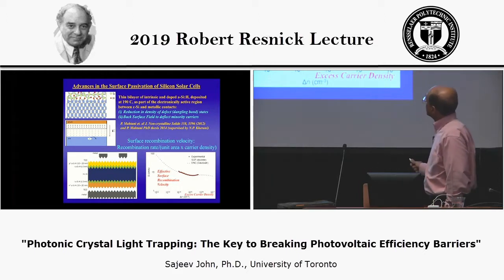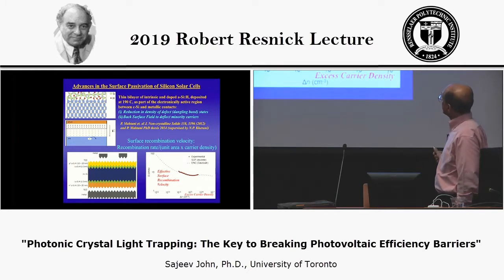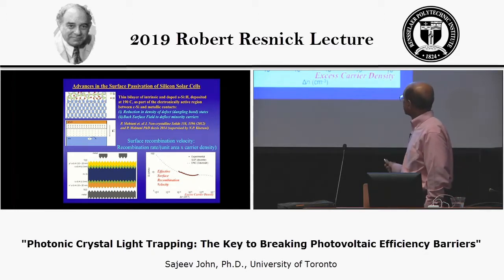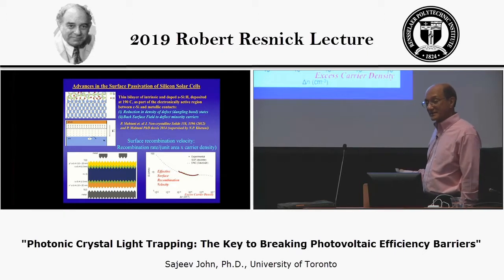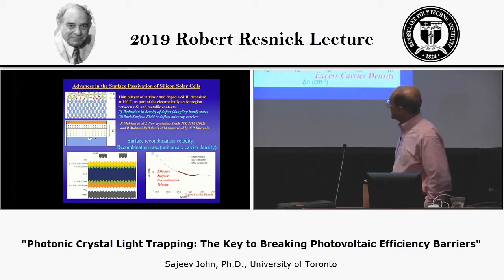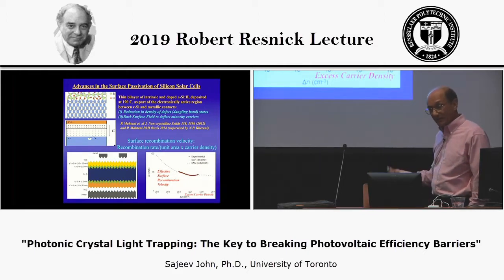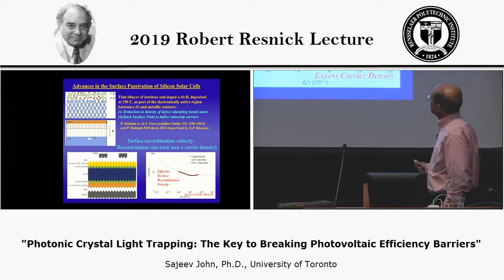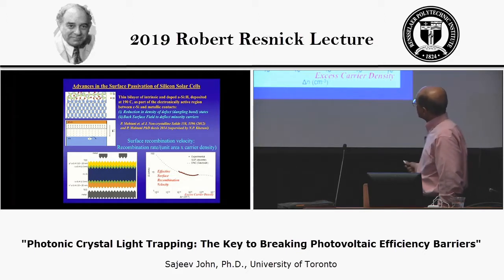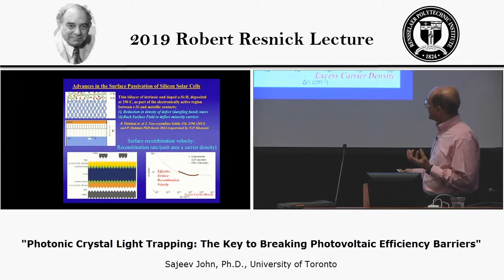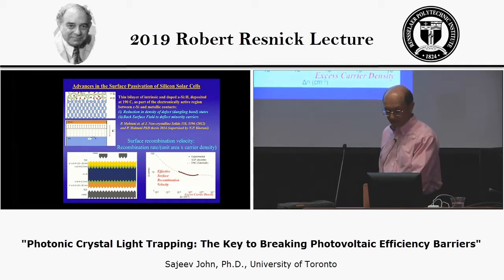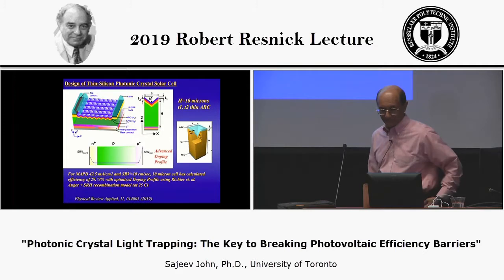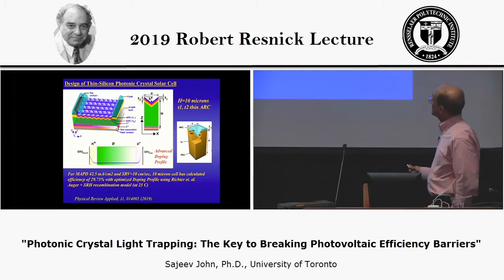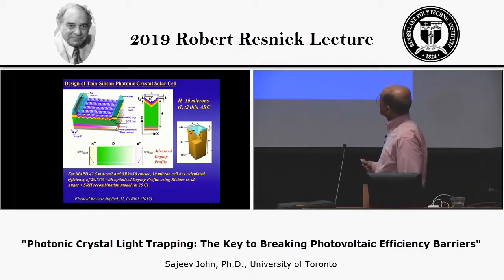And they were able to demonstrate what is called the surface recombination velocity, which is the recombination rate per unit area, per unit of carrier density, as low as about 10 centimeters per second. So this is sort of the state of the art, and that occurs for the regions near the contacts, which is where a lot of the recombination takes place. So this is one of the state-of-the-art achievements, I think, in terms of passivating the contact regions, and those are some of the numbers that I'll be making use of in our model describing the drift, diffusion, and recombination effects.